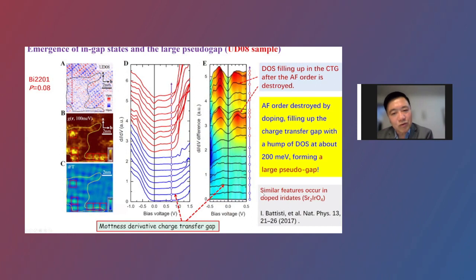It is quite interesting to mention that actually in these iridates, Alain Milan's group also measured tunneling spectrum. They also see this kind of large pseudo gap. So for the strongly correlated system, it seems they are behaving in a very similar way.